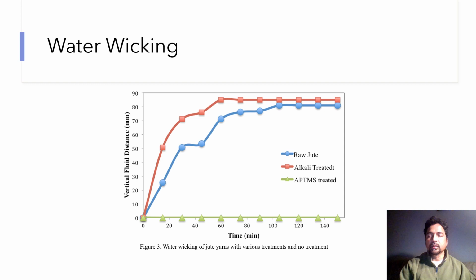However, when you do alkali treatment, we remove lignin and hemicellulose from the jute fiber, which will actually open up the jute fiber. That will allow it to absorb more water compared to raw jute. However, when you do APTMS silane treatment, all the jute fibers would actually become hydrophobic. As you can see, the green dots, which are on the x-axis, have zero water absorption. Hence, we want to confirm that it's very important to make the jute fabric hydrophobic before we use it in the composite fabrication.